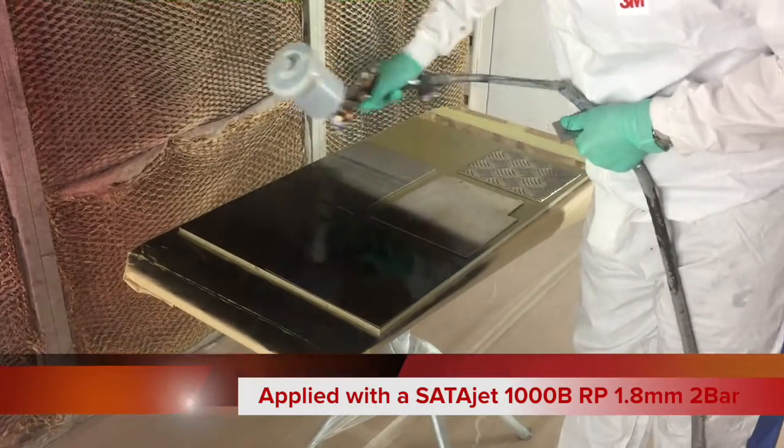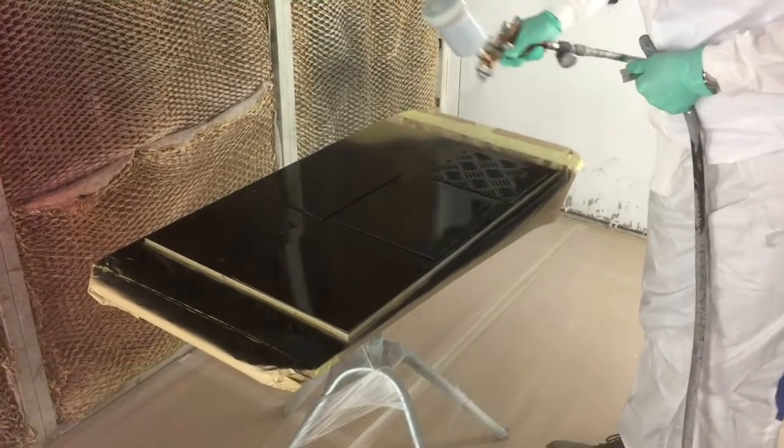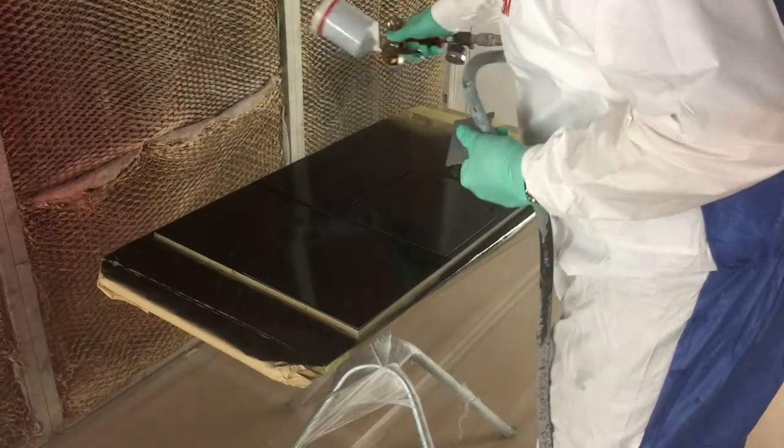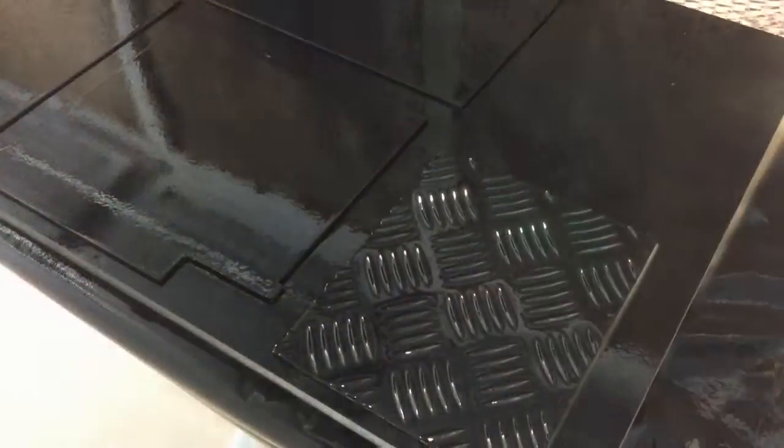Once applied, Oropal 472 is dust free in 2 to 3 hours at 20 degrees Celsius and fully dry after 12 hours. Where quicker through drying is required, then high temperature curing may be used.